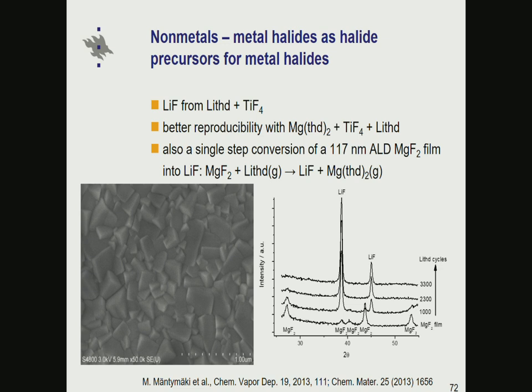And the magnesium fluoride was 117 nanometers in thickness, and with increasing number of lithium THD cycles or exposures, it was completely converted from magnesium fluoride to lithium fluoride. So all the magnesium was converted away through these reactions with lithium THD. So this is kind of an unconventional looking non-metal precursor.